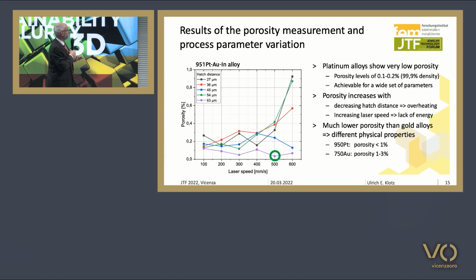Anyway, we found very low porosity values. So this is 0.2% porosity, which means 99.8% density. And it's easy to obtain values below 1%. So we can obtain values of 99% density, which is more than comparable to cast platinum objects.